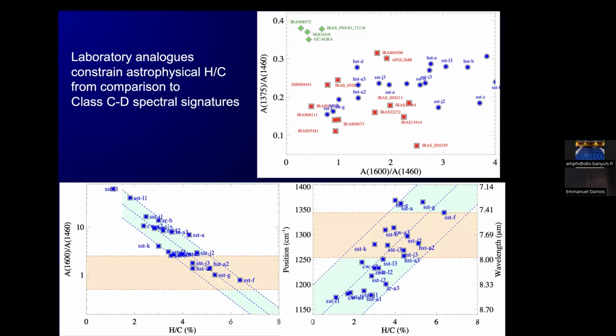So you have a good correlation here, and you can get from independent measurements the amount of hydrogen over carbon you get into the system that would cope with what is observed. And in fact, you realize that you don't need such a high percentage of hydrogen to get the features you are using here. It's only a few percent, so you're in a very reducing environment. But in fact, the backbone structure does not necessarily need to be extremely hydrogenated to produce what you are observing.